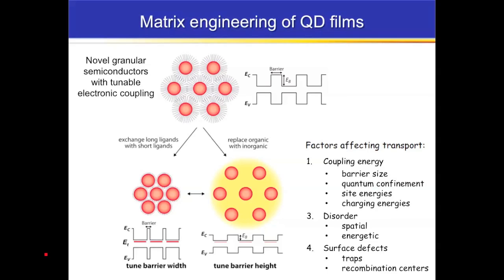So these materials, these quantum dot solids, are a new kind of granular semiconducting material. And we can understand charge transport in these materials by considering them as arrays of conductive islands. These cores of the quantum dots are the conductive islands, separated by tunnel barriers, which have a certain width and a certain height. The width of the tunnel barrier is basically set by the interdot distance. And the height of the tunnel barrier is set by the electronic properties of whatever material is in the matrix. In the case of our starting material, it's oleic acid.